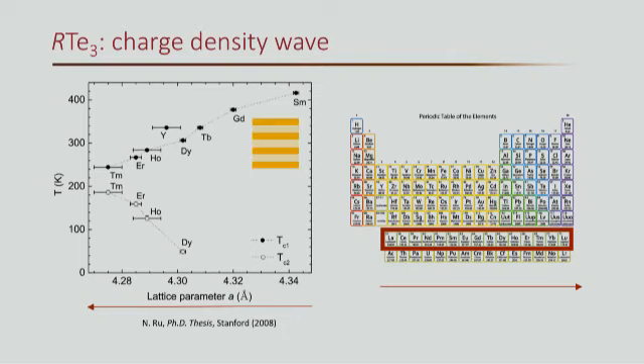So as we cool down below the first transition temperature, a one-dimensional charge density wave forms, and basically here is a cartoon picture to show there's something like a stripe order. For some of the rare earth atoms, especially heavier ones starting from dysprosium, as you cool down further, a second phase transition happens, which shows an orthogonal direction to the first CDW. So you can loosely call it a checkerboard pattern.